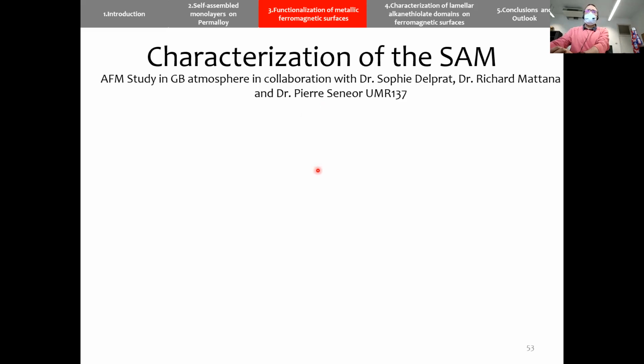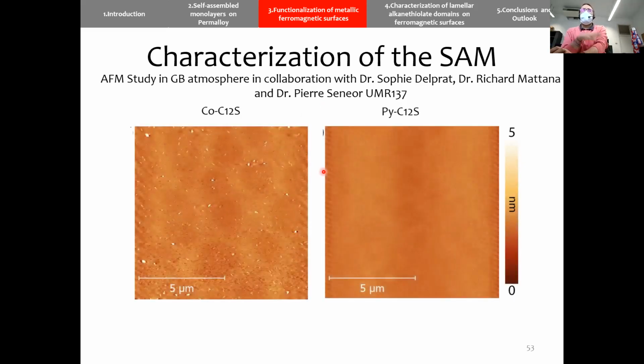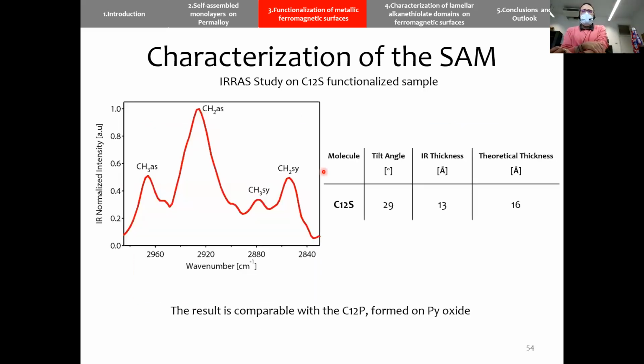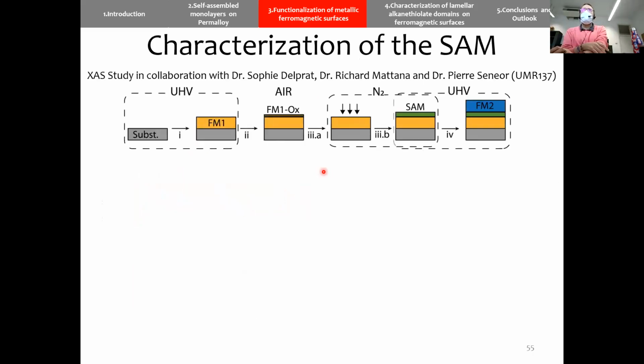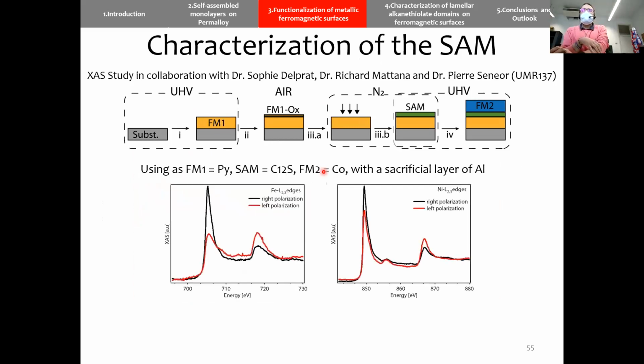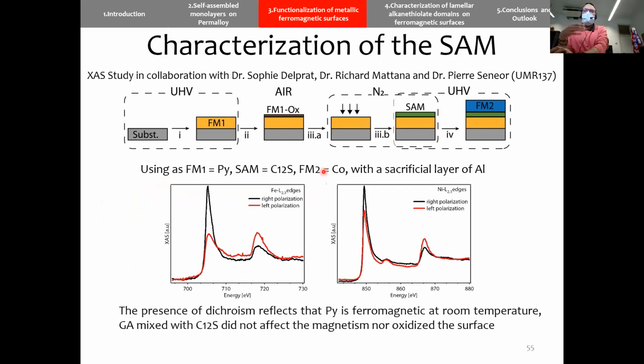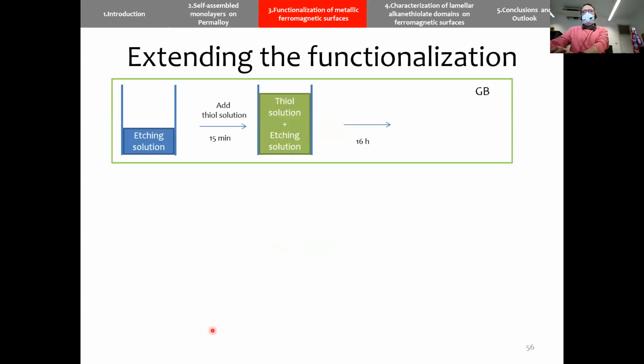And then we also checked that if we prepare it, the surface is very smooth. The infrared shows the formation of the SAM, and having done all this methodology, we did some SQUID measurements, and we observed the presence of ferromagnetism at room temperature. So this means that the full device is still ferromagnetic, or at least the bottom device that has been modified with a C12 dodecanethiol SAM is still ferromagnetic.